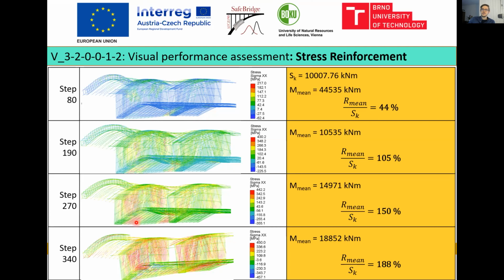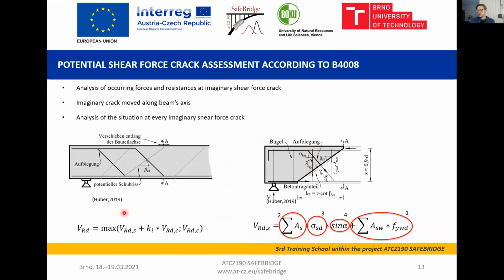You can see the high shear stress on the model and the high stress on the lower reinforcement of the concrete slab. One part was that the initial shear check in SOFiSTiK, according to today's load model, wasn't met. We had to perform a more sophisticated approach. In the Austrian ÖNORM B 4008, there's a multi-level approach, and if the initial checks are not met, you can choose between different approaches. For this bridge, the model for bars with bent reinforcement was selected.